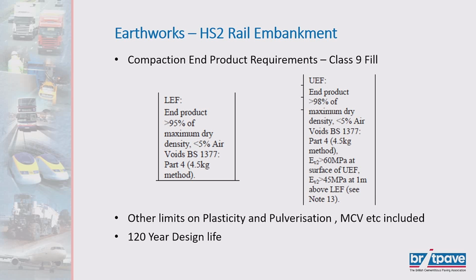It's one of the toughest specs we've achieved, and Steve, if you don't mind saying, it's actually proved quite tricky to achieve without significant additions of water and other materials in some of the materials we have within the UK. But once it's down and complete, and from our experience on C1, which is the contract at Maple Cross, once it's in and to spec, the HS2 spec, it's bulletproof. It's not going anywhere. And so then work through.